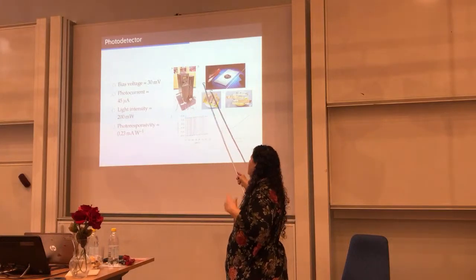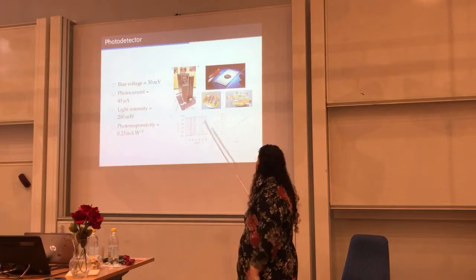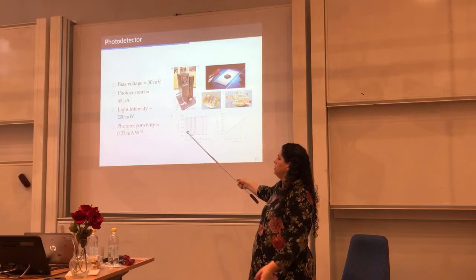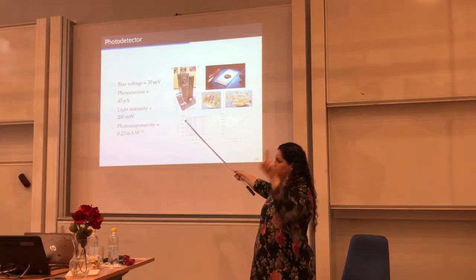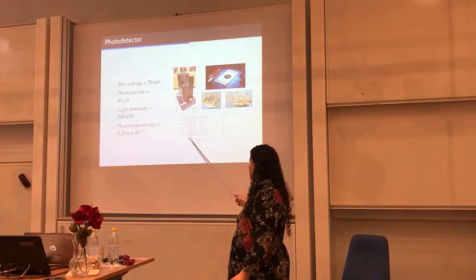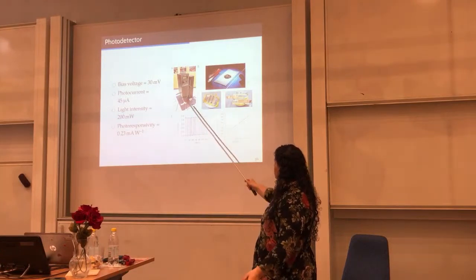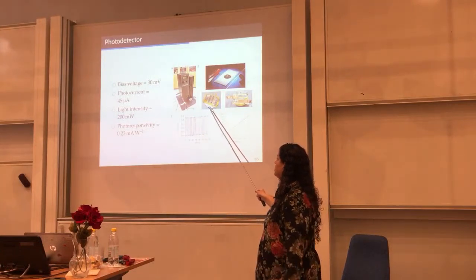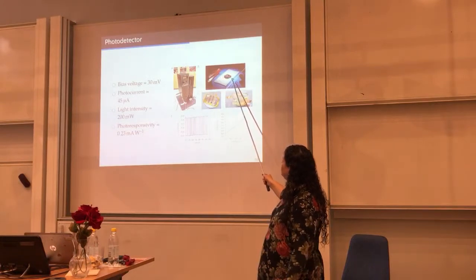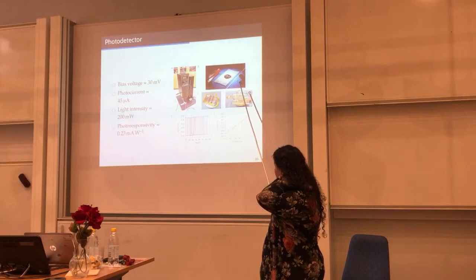So we turn the light on and off and measure the current. This is the current in the dark, and then you turn on the light, and this current will increase. This difference between the current in the dark and in the light is called photocurrent. So we did the same using these flakes, but instead of the gold wires like this, that was hard for us to measure, there was a lot of resistance here. So we got better results.